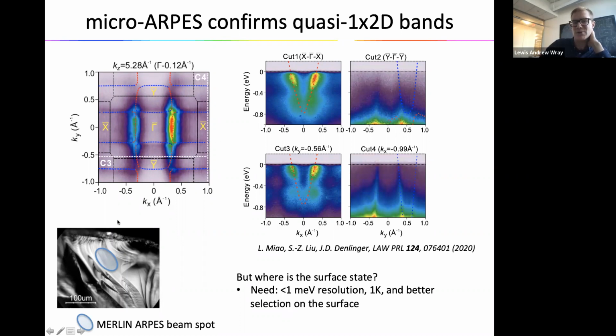If we really wanted to zoom in further, this study was performed with a 100 micron beam spot, and you can see what that looks like on the sample. Well, 50 to 100 microns. If one wanted to zoom in and have something truly homogeneous, so that the quasiparticles aren't going to look so broad, so you can get a clear look at perhaps the topological surface states in the superconducting regime, you would need to go significantly smaller.